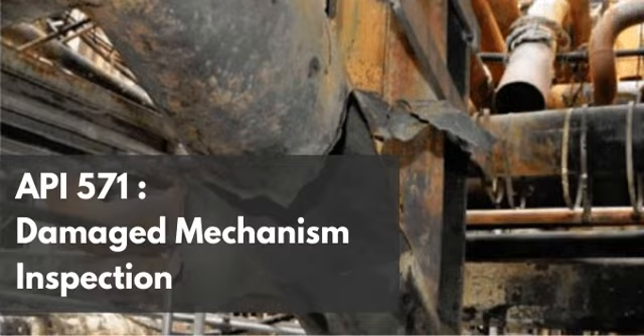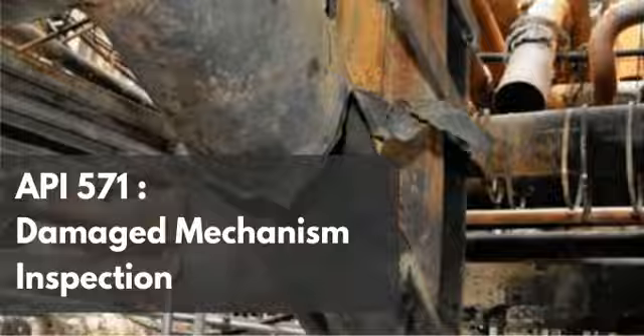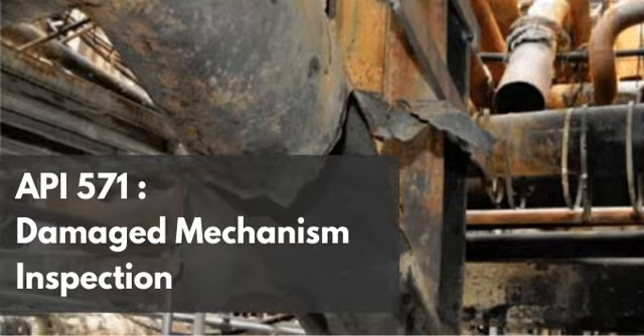Exactly. A thin lip rupture indicates ductile failure. It is what steel is supposed to do. The metal yielded, it absorbed energy, and it stretched until it physically could not stretch anymore. But remember what has happened to our carburized steel? It can't stretch. Right. It is no longer a flexible matrix. It is a glass-like network of chromium and iron carbides. It has lost all its ductility.